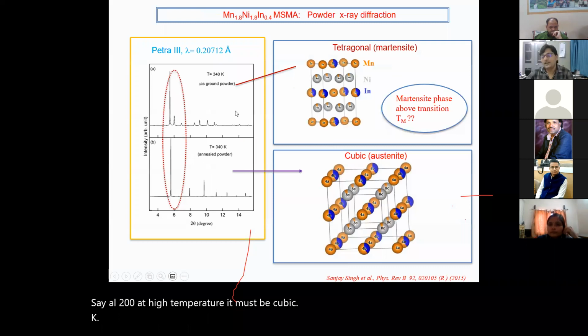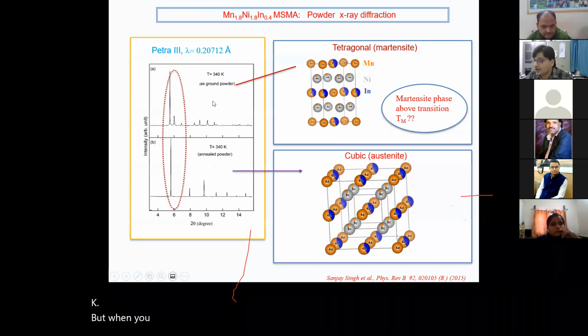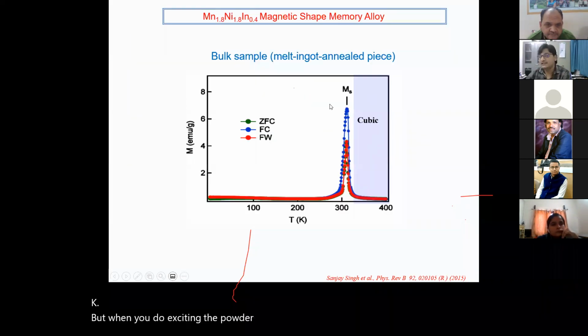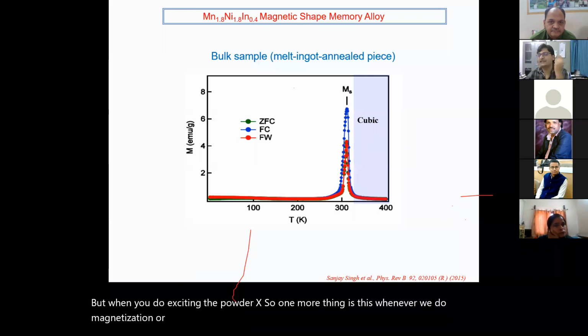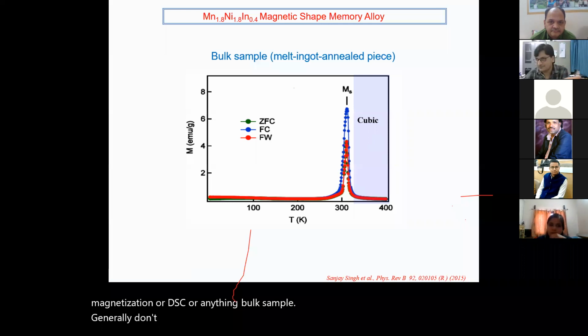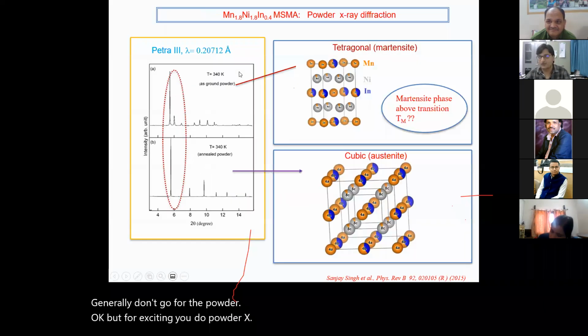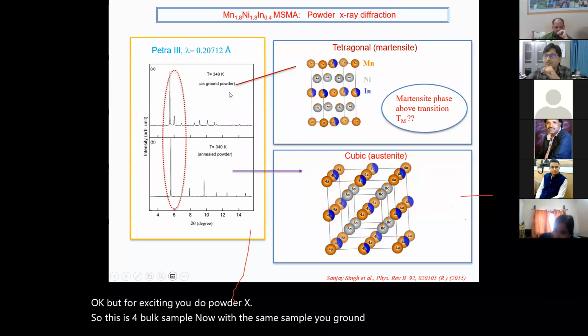But when you do XRD, the powder XRD. One more thing here: whenever we do magnetization or DSC or any characterization, we take a bulk sample. Generally, we don't go for the powder. But for XRD, you do powder XRD. So this is for a bulk sample. Now, when the same sample is ground into powder and you do XRD, what do you get?